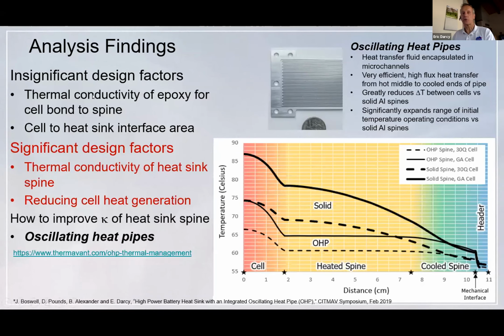And we found out that the thermal conductivity of the epoxy bond, we didn't have to use any fancy epoxies. It didn't really matter that much. And the contact area, that contact angle, whether we use 120, 80, 90, even down to 30 degrees of contact angle from the cell to the spine, didn't matter as much as the thermal conductivity of the heat sink spine. That's the big factor. And also anything we can do to reduce the cell heat generation. Going from the high energy cell to the high power cell really mattered quite a bit.